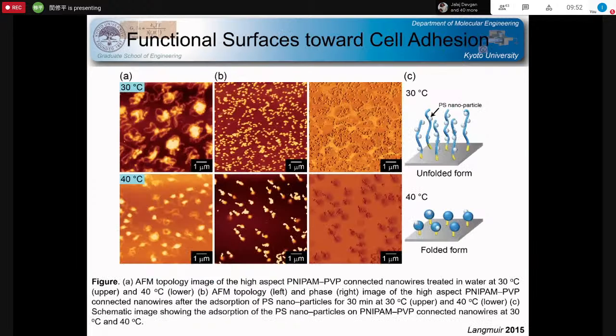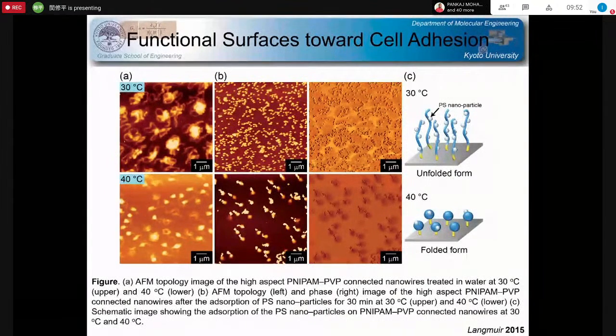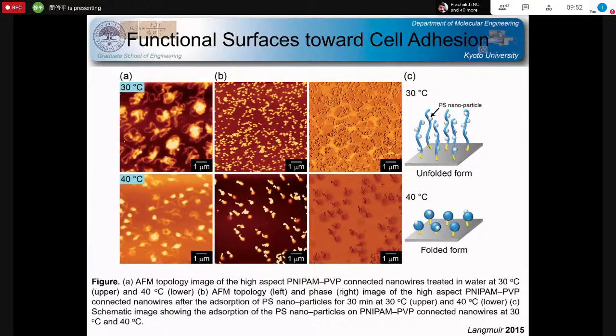And as I explained in the previous slide, we have successfully realized thermal-responsive one-dimensional nanomaterials. The morphological changes of the one-dimensional nanowires also convert thermal energy into kinetic energy. So when one segment of the nanowire is stretched, it has a very large surface area. In this form, the nanowire surfaces can interact with small particles. However, once the material is heated up, the nanowire shrinks, so the interfacial interactions with the small particles should be fixed at the certain point where the nanowire shrank.